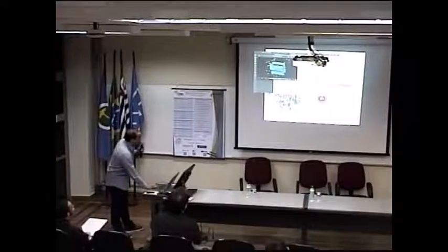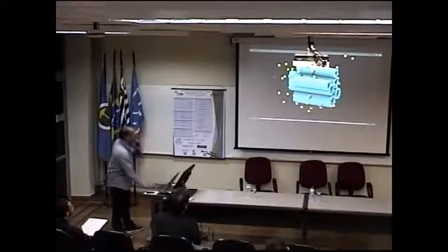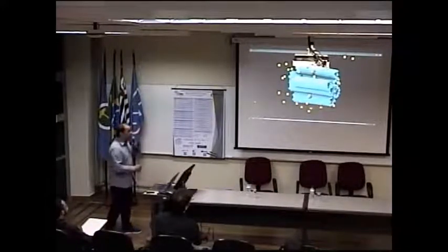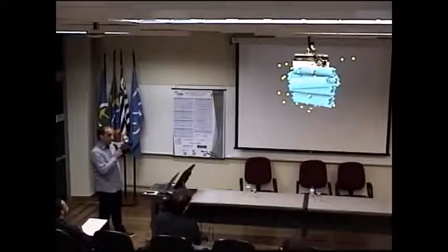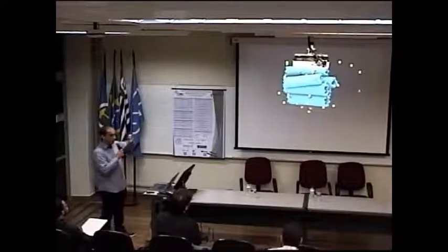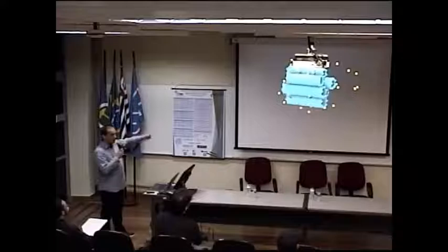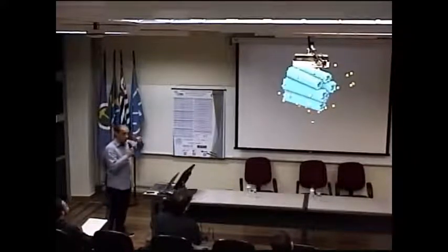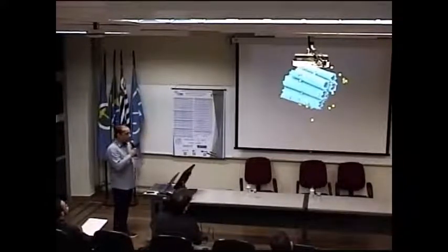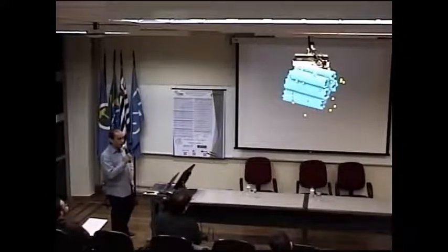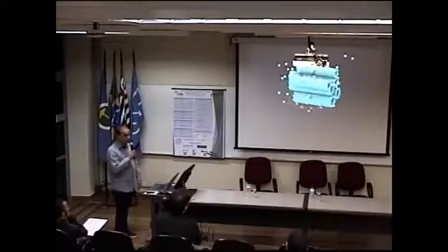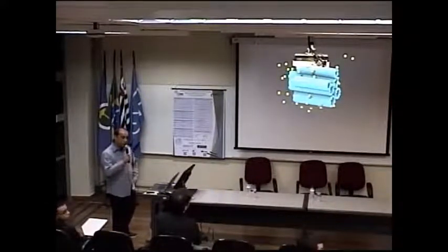Well, this is also something that is, in some sense, expected, because the force that drives it is the van der Waals interaction. And it's known that if some atom or molecule passes the barrier of the tip of the tube, the energy inside is lower than outside. Then there is a small energy well where the particles can be trapped. If you increase the temperature too much, some of them can go out again.